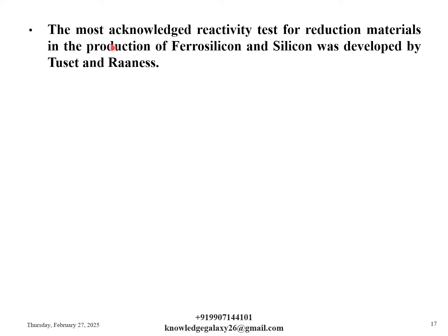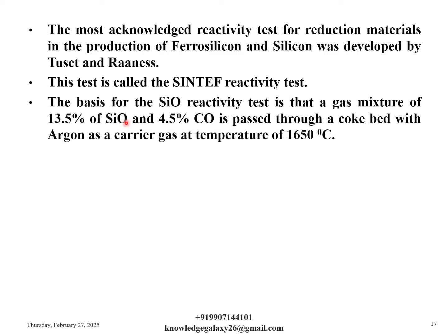Okay, now moving again first. The most acknowledged reactivity test for reduction materials in the production of ferrosilicon and silicon was developed by Tuset and Raanes. This test is called the SINTEF reactivity test. The basis for the SiO reactivity test is that a gas mixture of 13.5% SiO and 4.5% CO is passed through a coke bed with argon as a carrier gas at a temperature of 1650 degrees Celsius.